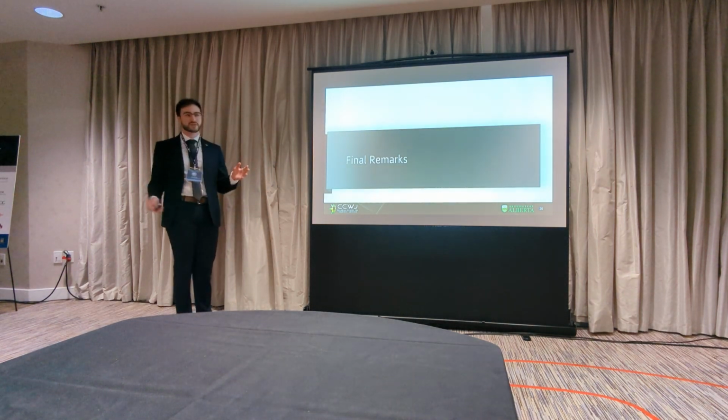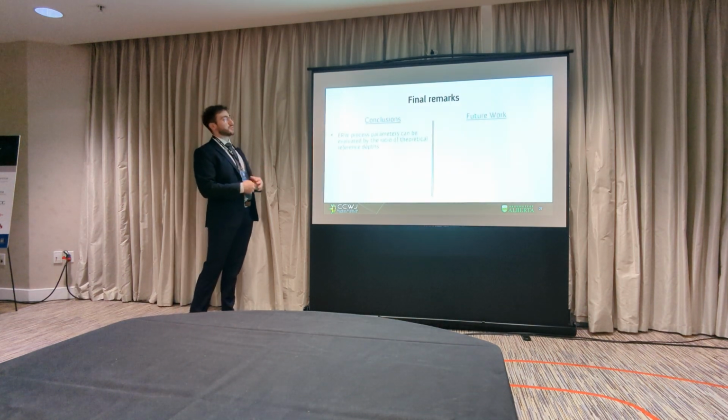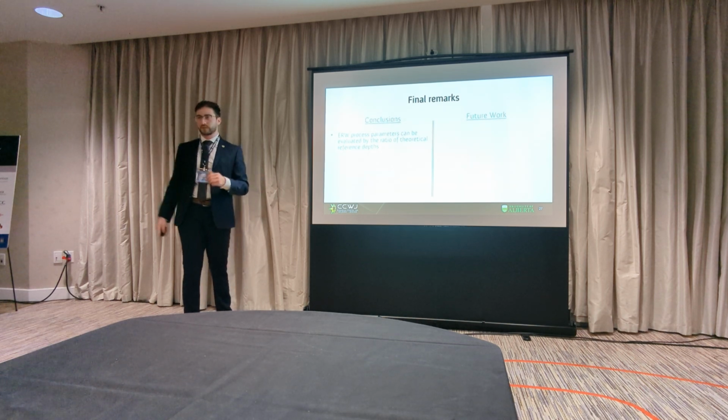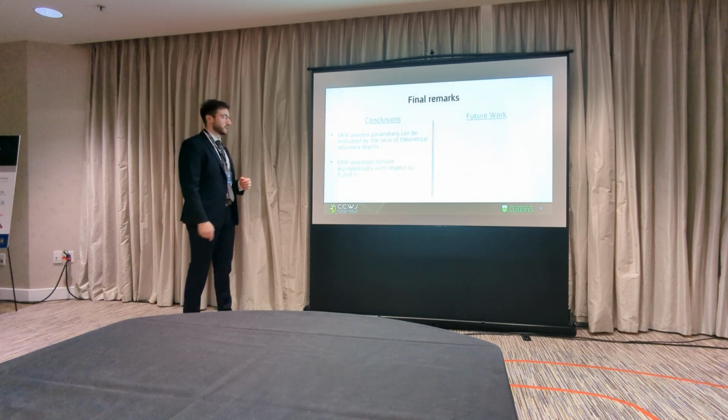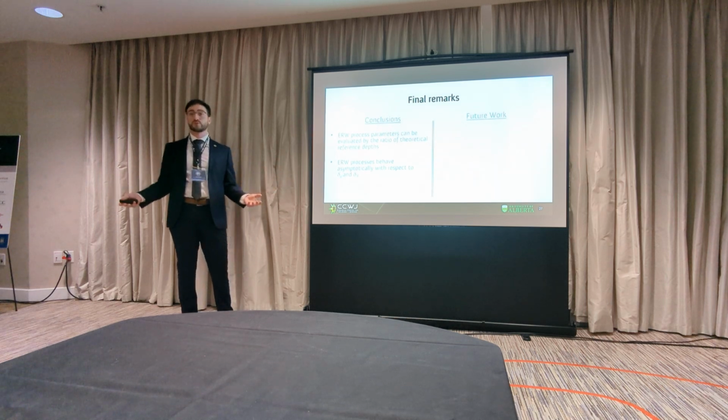So some final remarks. ERW process parameters can be evaluated by the ratio of theoretical reference depths. That's the thermal depth and the electric depth that I was talking about earlier. They behave asymptotically with respect to the skin depth and the thermal depth, which means that it has two different modes or two different potential regimes of operation.